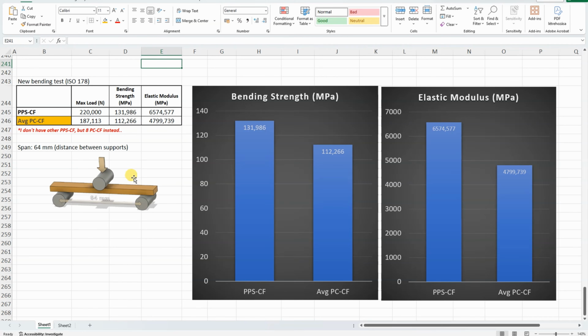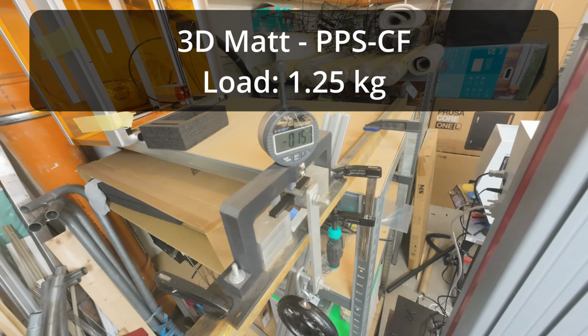In this test I don't have even one PPS-CF filament, so I will compare it to the average PC-CF, and I have 8 pieces in the summary table, and we can see both bending strength and elastic modulus, so this PPS-CF is very strong.